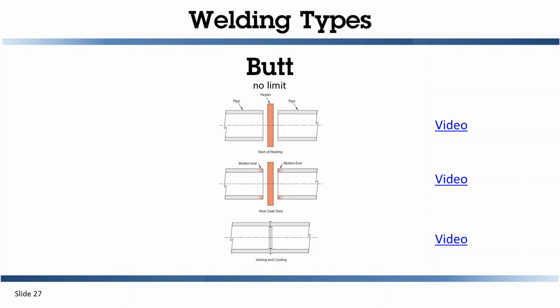Butt fusion, like I mentioned, has no size limit. You have the pipe that's compressed against a heater. After a certain amount of time, you remove the heater and push it together. This is done with a welding tool that is rented or purchased from the manufacturer, and you have to follow the prescribed welding times and cooling times for this. Because there's no coupling here, you're actually reducing the overall labor to weld and install this. You just have pipe to fitting with a butt fusion weld.